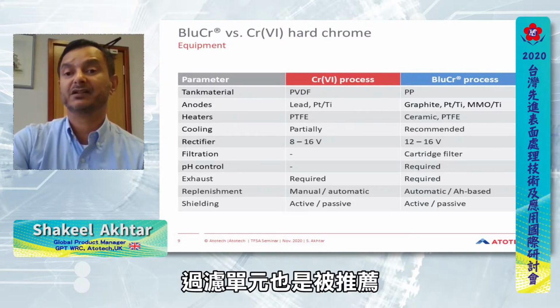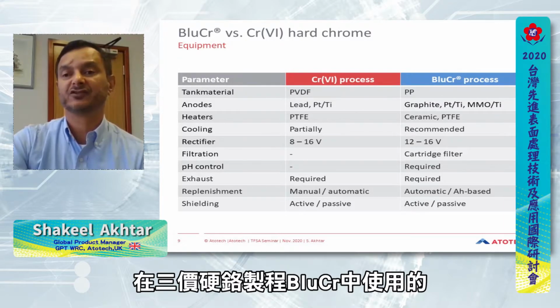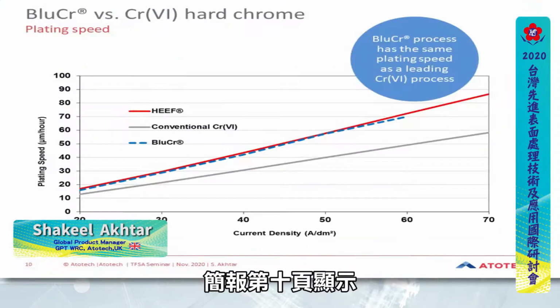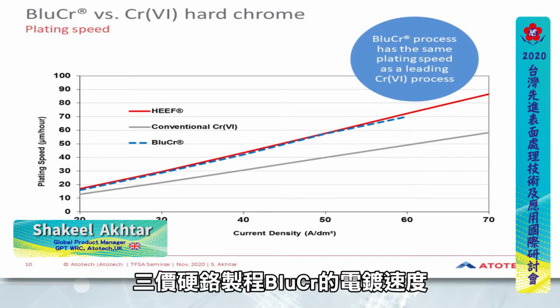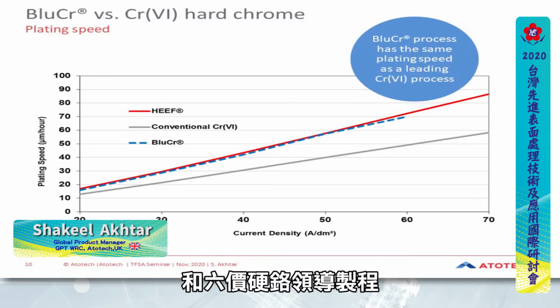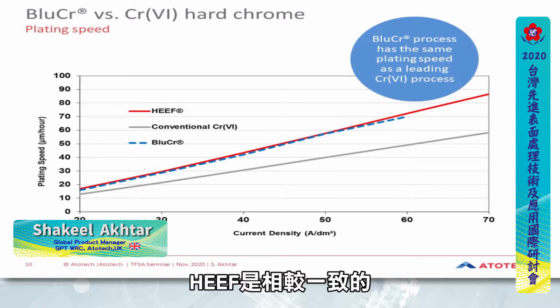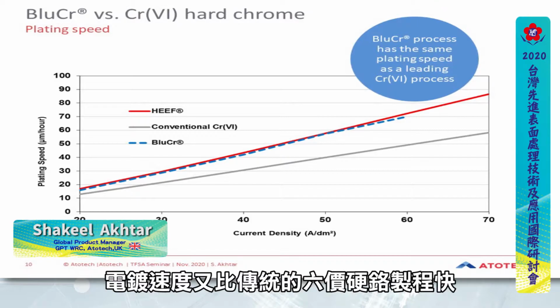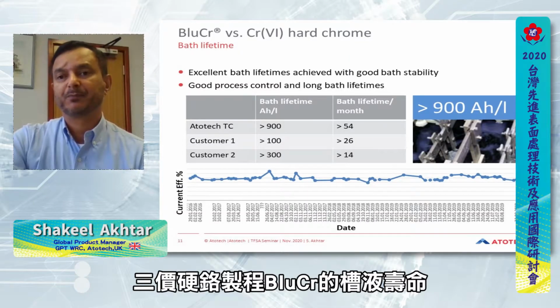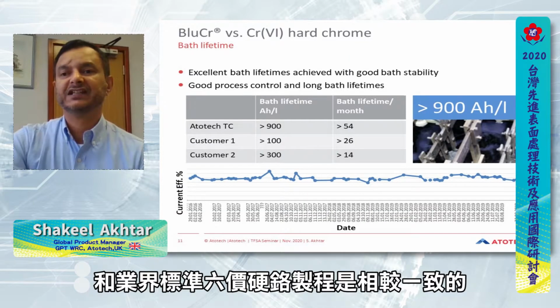The additional requirement is that the blue chrome requires filtration of the bath as well. Slide 10 shows the plating speed of the process in that it's comparable to the leading HEEF process under the same cathode current density conditions and is higher than the conventional hexavalent process. The bath life of the process is comparable to the industry standard hexavalent process.